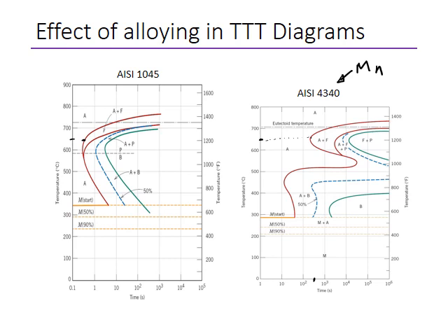So when you are quenching a part that is very thick, the microstructure will change a lot from the surface to the center because the time for it to change temperature is very different. So by alloying with manganese, silicon, and other elements, you can give more time for the material before transformation takes place.